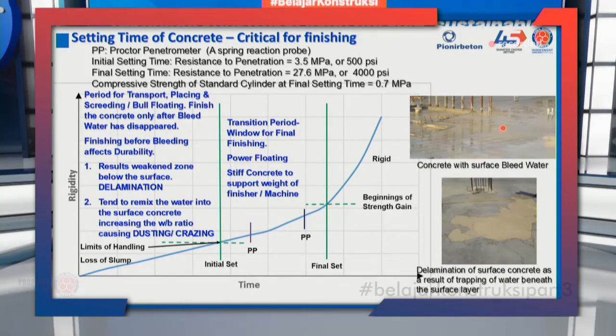So now when the bleed water comes, what should you do? Should you finish or not finish? Don't finish. Wait until all the bleed water disappears. If you do not care, and simply finish the surface, the top layer becomes very weak. The water cement ratio of the top layer will be very high, and it is going to cause dusting and crazing. Okay, this should not happen.